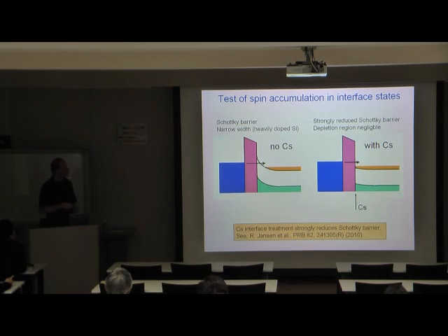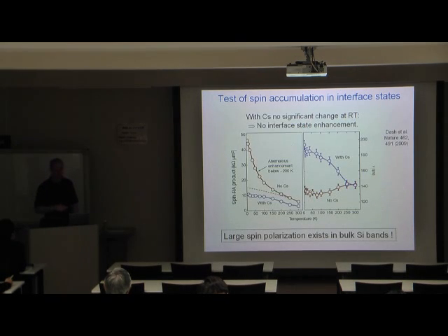And if we do have this enhancement, and we then remove the Schottky barrier, then we expect a large drop in the signal by several orders of magnitude. What we observe in our experiments is basically not much of a change, certainly not at room temperature.